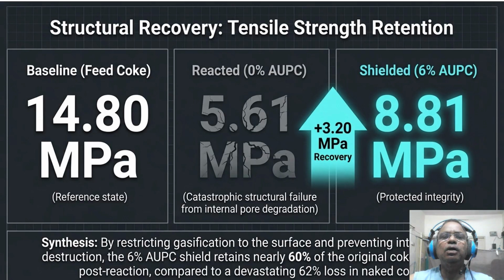So now coming to this slide, which is about tensile strength retention. This is the payday slide. This is why we care about unburned coal ratio. Look at the center. Reacted coke without a shield dropped to a terrifying 5.6 MPa. But with that 6% AUPC shield, we are at 8.8 MPa. That is a plus 3.2 MPa recovery.